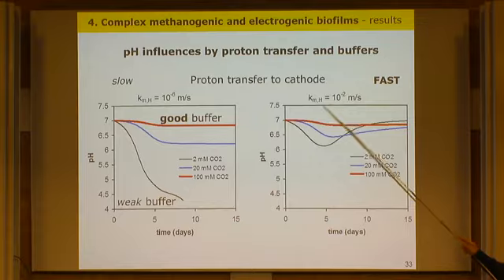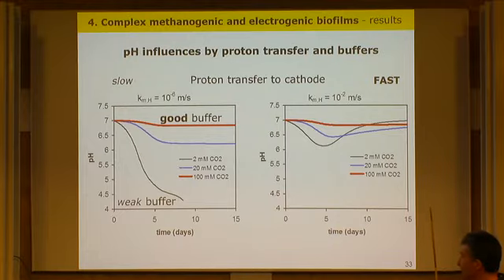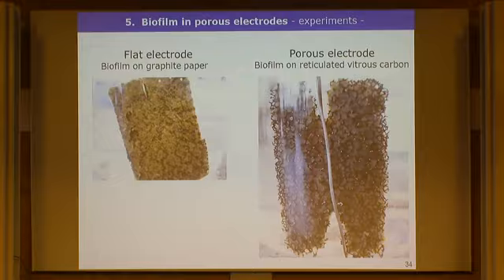And another mechanism would be the transfer through the membrane to the cathode. So if you don't have enough buffer, at least you should be able to transfer protons to the cathodic space. And this can also be very limited, because actually people noticed that it's not the proton which is transferred, but mainly the sodium ions. These membranes transfer any positive ions, any cations. And you know, proton pH concentration 10 to minus 7, sodium about 3 orders of magnitude more. So it's mainly the sodium transferred and not the proton. They are not very effective, these membranes.